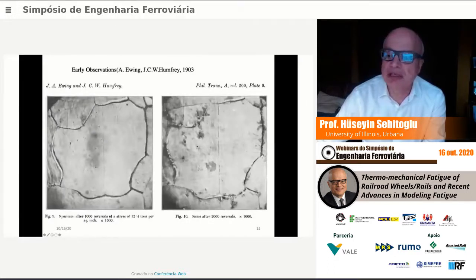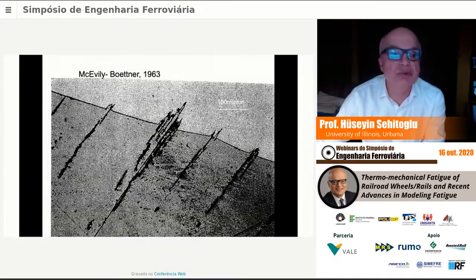show that fatigue crack nucleation initiates at grain boundaries, and these are probably favorable grain boundaries. And you could see here, this is most likely a favorable slip system, and there are some slip systems active here, slip bands that become fatigue cracks. Again, these cracks could traverse across the grain, as shown in here. This is the picture after 1,000 reversals. This is the picture after 2,000 reversals. So there's some cracking here, but they haven't grown, or they're not as visible. While here, this is the work of Ewing and Humphrey.